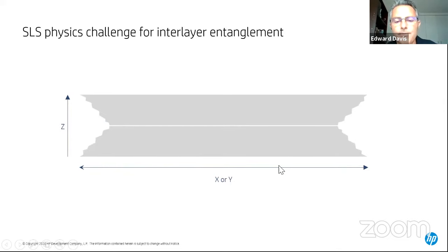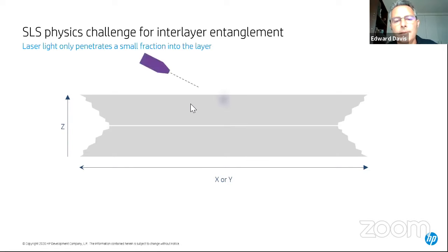So in this picture, the horizontal is X or Y, it doesn't matter which. The vertical is Z. The bottom portion here is one layer, and this top portion is the next layer. The weakest point in all of these layering processes is between layers, okay? It always is the weakest point. What happens with laser sintering is that you blast the laser into this powder bed, and you try to melt where you want the thing to melt.